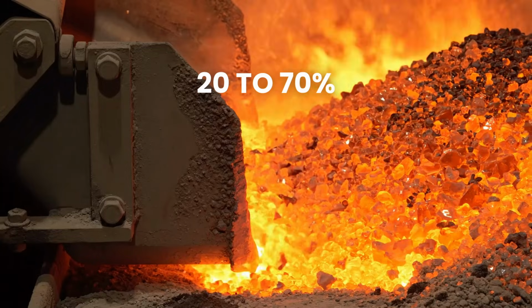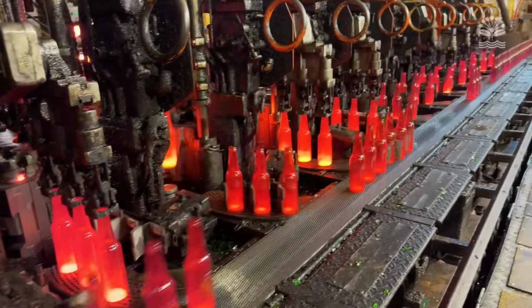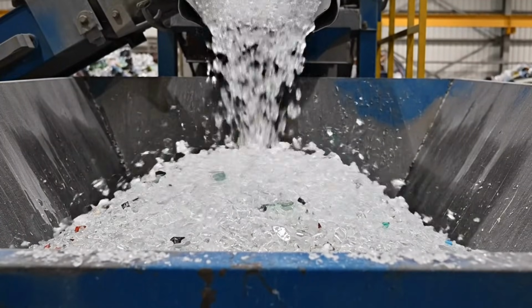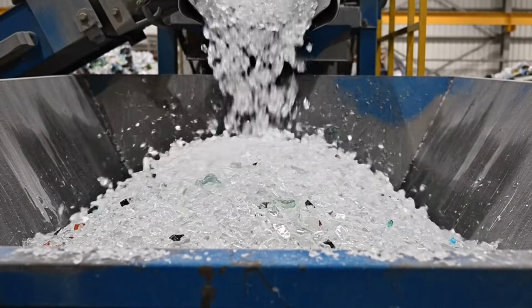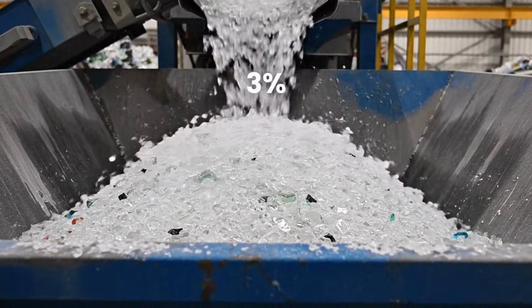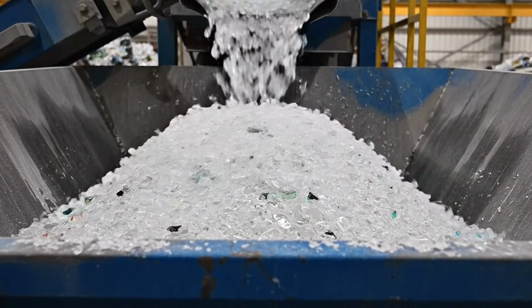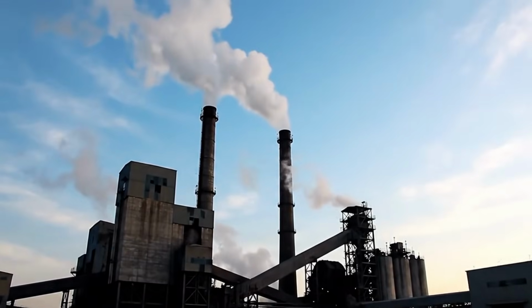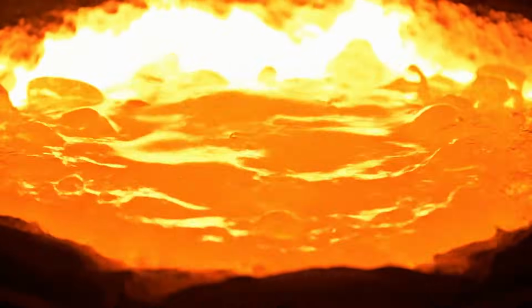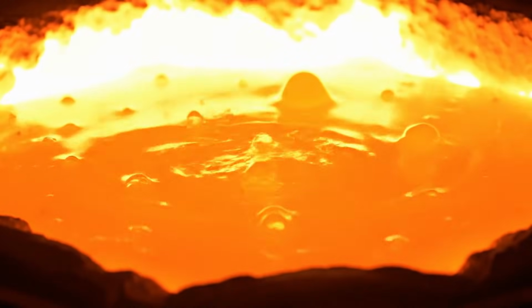The role of cullet: recycled glass typically comprises 20% to 70% of the total batch. Here's why this matters. Every 10% increase in cullet content reduces energy consumption by approximately 3%. Using cullet significantly decreases carbon dioxide emissions. Cullet melts more uniformly, improving overall product quality.